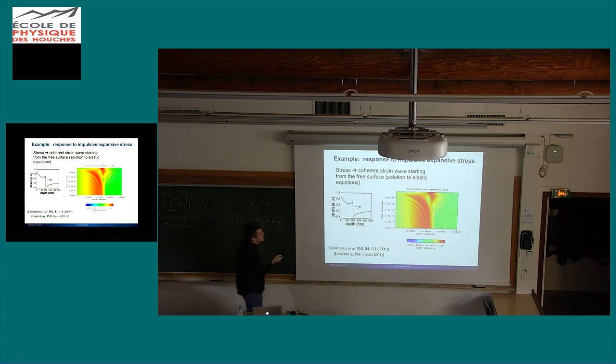And in X-ray diffraction, there are different ways to think about this. One way to think about this is you can see interference between the surface of the crystal. So this is at 0 depth. That's the surface of the crystal. And this discontinuity essentially gives you a border between two regions of the crystal that have a different lattice spacing. And you get interference also from this and from this interface between these two crystals. And that results in this sort of fringing pattern that develops as a function of time, because this is moving as a function of time, and so the spacing of the fringes will change also with time. So this is the angle that you are deviating from the Bragg condition, and this is time in seconds. I don't know why it's in seconds, but okay.